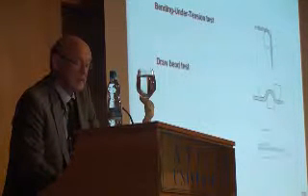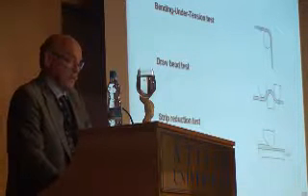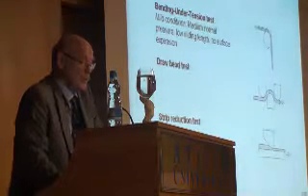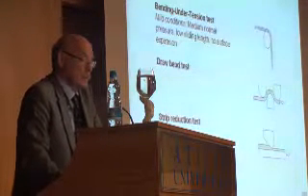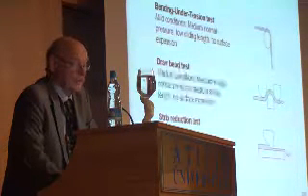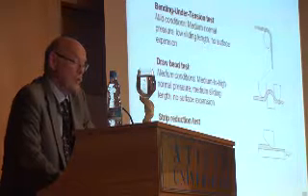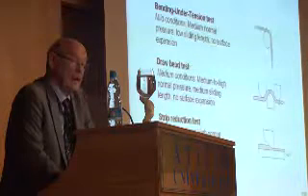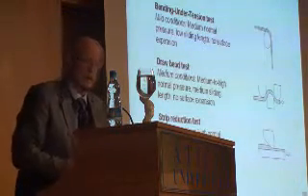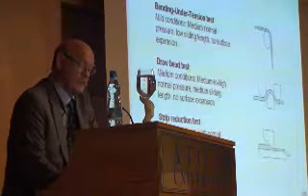We have chosen 3 simulative tests, namely bending under tension, drawbead test, and the strip reduction test. The bending under tension has mild conditions with low to medium normal pressures, low sliding length and low surface expansion. The drawbead test is somewhat more severe with higher normal pressures, but still no surface expansion. And the strip reduction is really not a sheet forming, it's a bulk forming with surface expansion involved and bulk deformation.